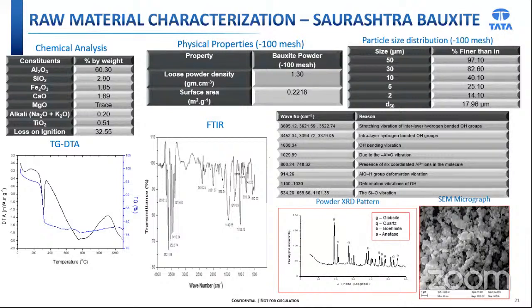Now coming to the results and discussion portions. First is the Saurashtra bauxite raw material characterization. Chemical analysis of the bauxite reveals that alumina is the main constituent with minor presence of silica and iron oxide. The typical loss on ignition value of the bauxite indicates that it is the gibbsitic kind of bauxite. The high value of LOI is attributed to the presence of both interlayer and hydrated water.